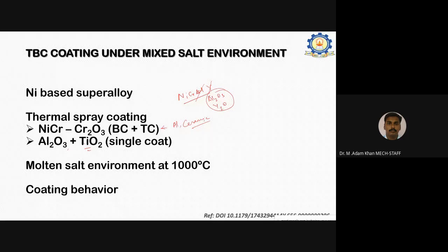So in early days before doing my research, I could see Al2O3 plus 13% TiO2, 13% titanium oxide. After that I thought, why minimize the titanium? Why not go with 40% titanium? I thought this titanium may increase the bonding strength as well as reduce the surface tension, that is the self-cleaning property and everything. So I have done that 40T, that is alumina with 40% titania. After that I didn't get any coating powder with increased titania.